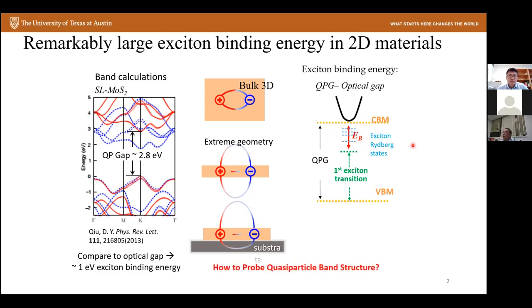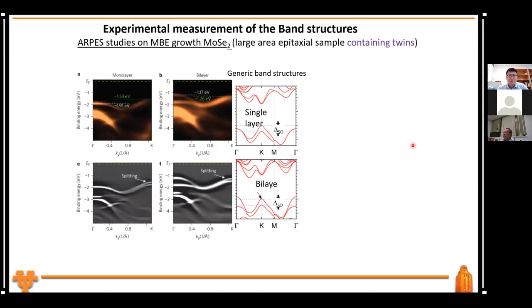So how do you probe the quasi-particle band structure? The most straightforward thing is let's just go ahead and use ARPES, right? Angle-resolved photoemission spectroscopy, measure the energy versus k, and you can map out the whole band structure. But ARPES usually lets you measure only the valence band. So this has been mapped out in this paper in 2014.